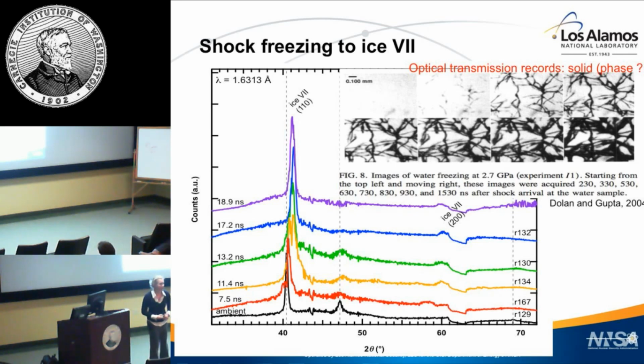Dan Dolan and coworkers executed a set of nice compression experiments on very pure water, looking at the shock freezing of liquid water to a solid. And you can see that on the order of hundreds to thousands of nanoseconds, they see changes in optical transmission geometry, okay, that would imply you're solidifying a material. But what is this material? Is it crystalline? Is it amorphous, a high density amorphous H2O? We didn't know. Moreover, is this really the time scale? Does it really take hundreds of nanoseconds to compress into a solid phase?